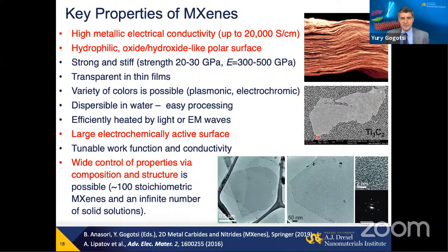These are single-layer flakes, produced basically just by separation by filtration on a substrate. And you can see TEM images of flakes, which actually repeat the crystallography of the MAX phase precursor. But what is important here, you see this flake is hanging over a hole, and graphene would not be able to support itself, but MXene is much more rigid, and it does.